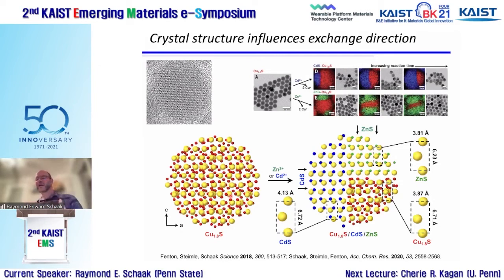If they remain segregated, they need to form an interface, right? Because we force them into the same particle, but they want to form an interface. And interfaces are inherently high energy. And so the interfaces that form, you're going to get the smallest number of interfaces possible, typically. You're also going to get the interfaces along the crystallographic directions that are matched best in their spacing. So where, let's say, the sulfur-sulfur spacings or the lattice constants are similar.